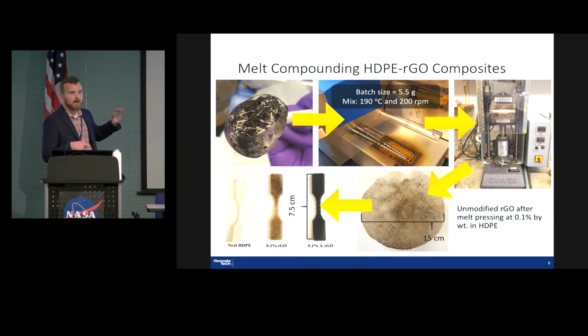And then from this, we can cut whatever shape sample we want. Shown here in the bottom left, I've got three dog bone samples. The one on the left is neat high-density polyethylene, which it doesn't look like you can see very well from up here. It's blown out a little bit, but what you can hopefully see is the difference between the two samples with 0.1 weight% of reduced graphene oxide shown here.